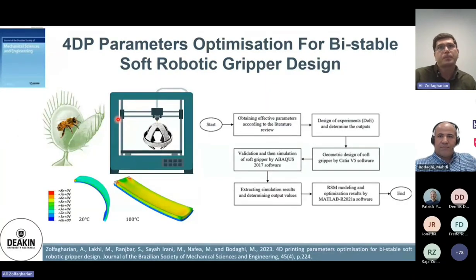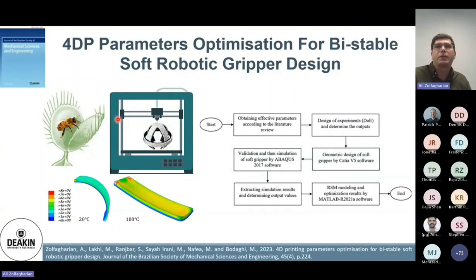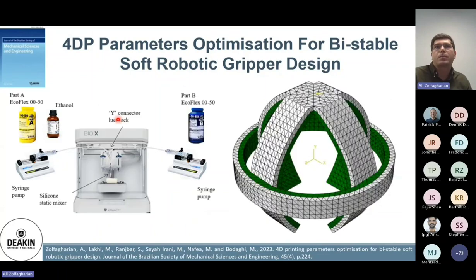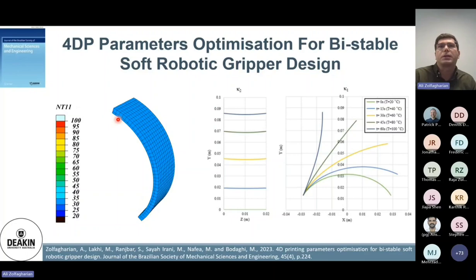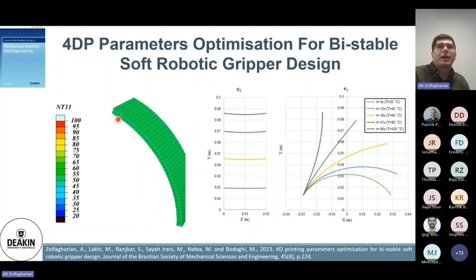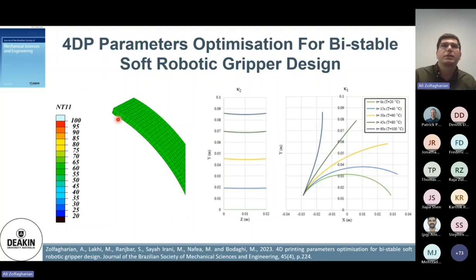And again, we keep using silicone as a pre-strain for developing different soft grippers. These are inspired soft grippers that you could see are pre-strained, and they have a bistable mechanism that we could achieve using this sort of actuator.